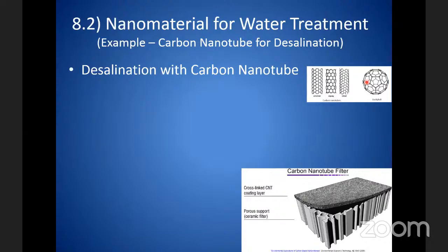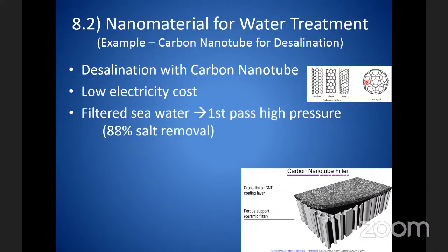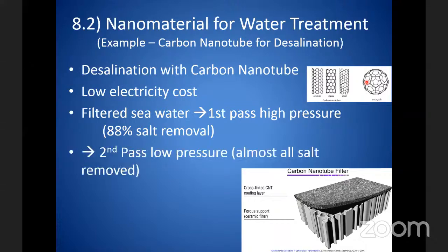This is the one which is almost coming to industrialization. Most of these nanomaterials for water treatment are still in the laboratory and pilot. Only this one is coming, but it's still fine tuning. So low electricity cost, how does it work? Instead of the 60 bar pressure for the RO, it is slightly higher pressure. The first pass at higher pressure will remove 88% of the salt. The second pass goes through the carbon nanotube filter. It will remove almost all the remaining salt.